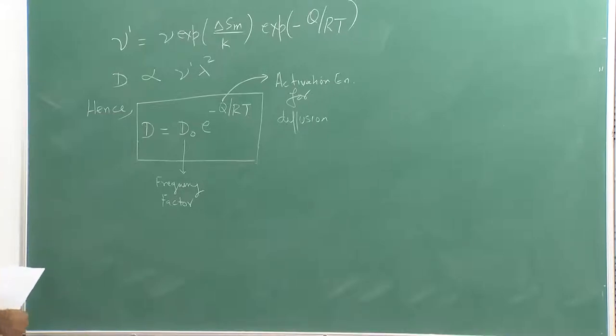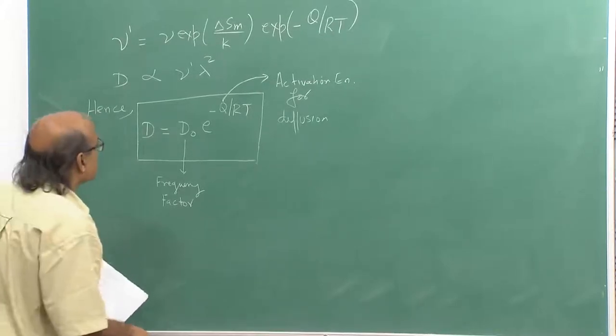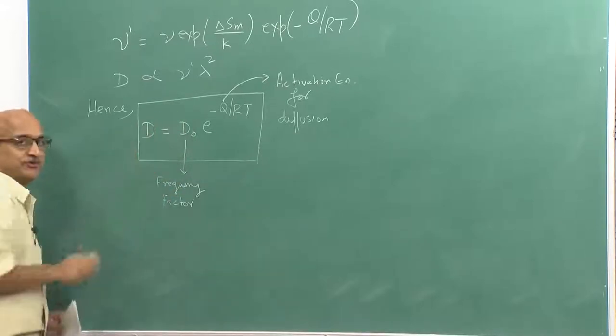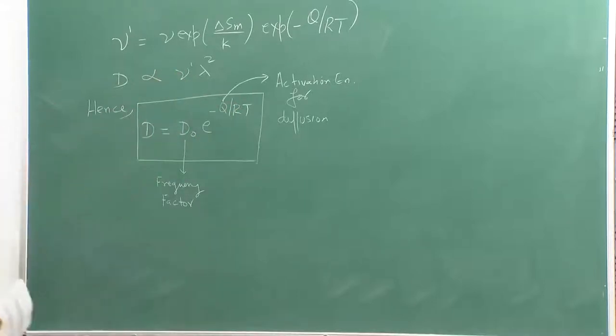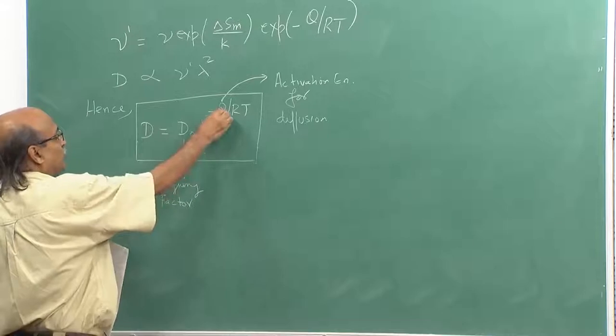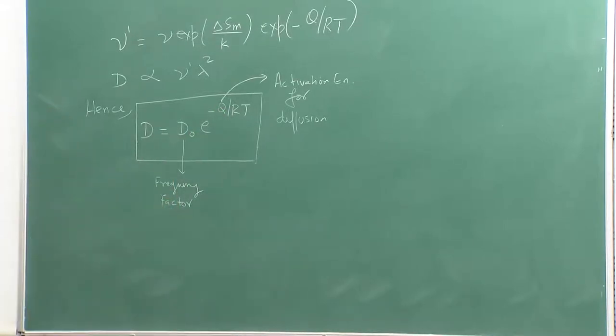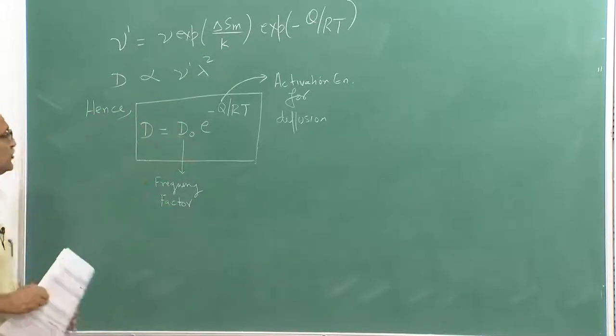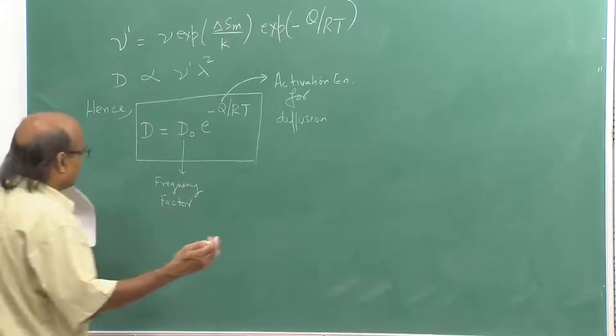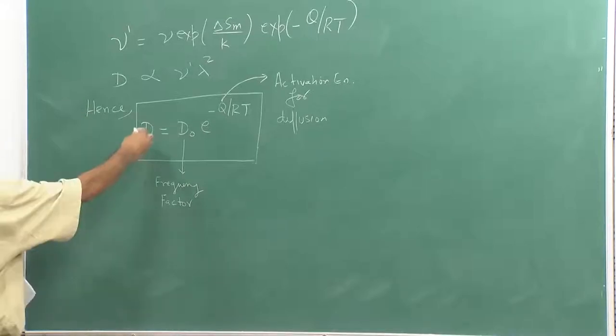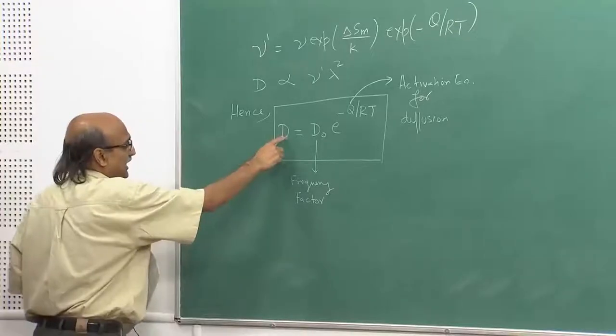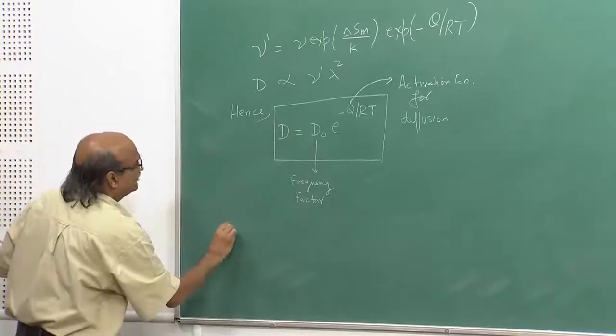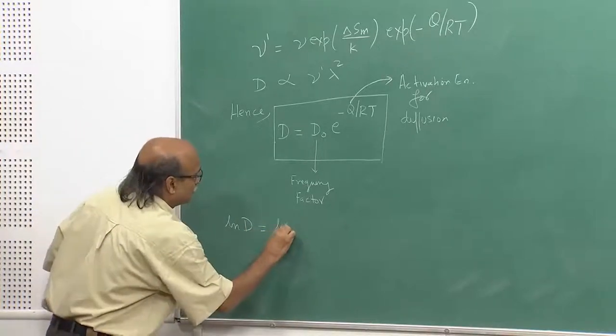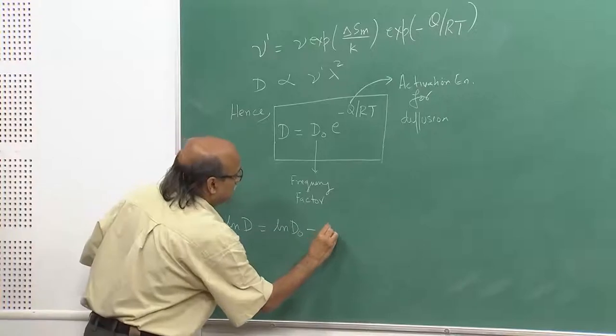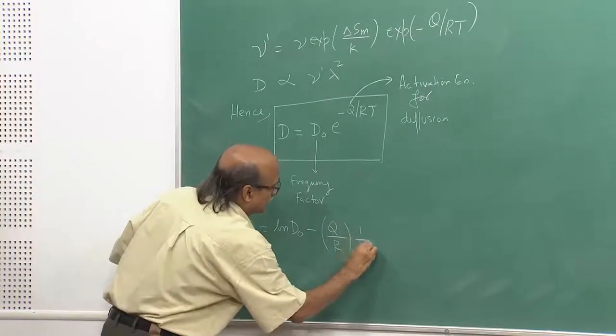And one final thing before I terminate this discussion in this lecture. If I collect different values of diffusion coefficient from diffusion experiments as a function of temperature, then I can find out Q and D0 from that data, and then I will be in a position to determine D for different values of temperature. And how can I find Q and D0? I will get diffusion coefficient values D for different temperatures, and suppose I take logs of this equation, then log D is equal to log D0 minus Q by R times 1 upon T.